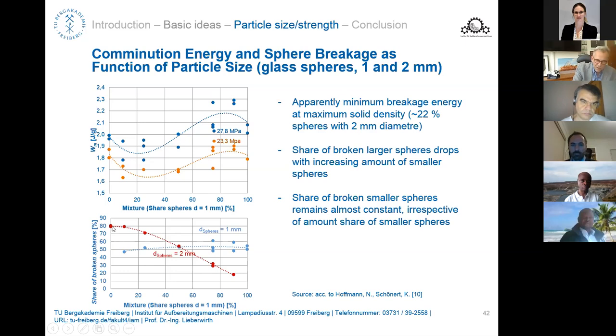On the other side, and this curve is also interesting, particularly if you're thinking about selective comminution, we have the number of the 2 millimeter spheres here. If we use a certain energy level, of course, if you have no fine spheres, you have 80% of the 2 millimeter spheres broken. So we add 10% of the fine spheres. Still, we are close to this one because the fine spheres fit somewhere in between. And then we increase the number of fine spheres, and we see that the coarser particles are not broken anymore, or to a lesser extent are broken.